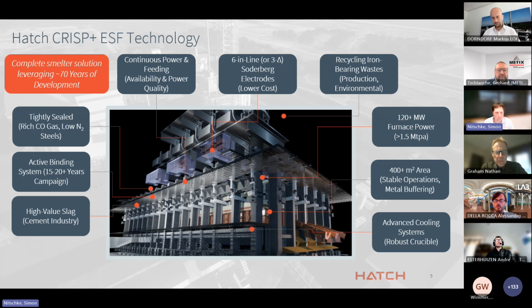And certainly powers up to 120 megawatts on a single 6-in-line furnace can pragmatically match those modern blast furnace replacement capacities with only 2 or maybe 3 units in some cases. Those furnaces themselves at 120 megawatts, we envisage being about 400 square meters in hearth area, and they are well within the known and proven smelting power density limits that are demonstrated today in some non-ferrous applications. The size of that furnace provides very stable metallurgy and in fact also provides buffering capability to upstream and downstream operations.